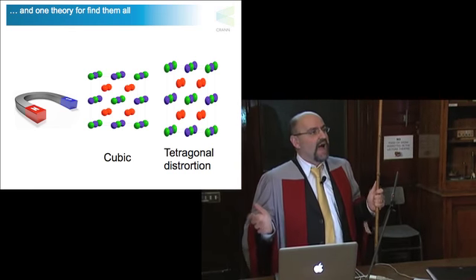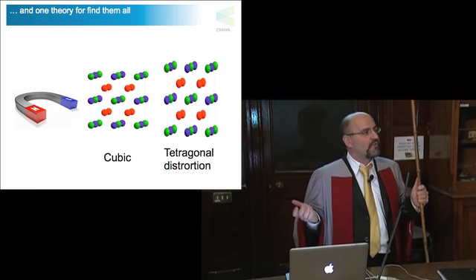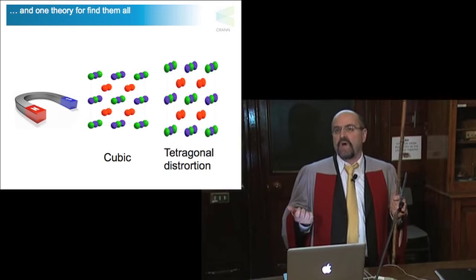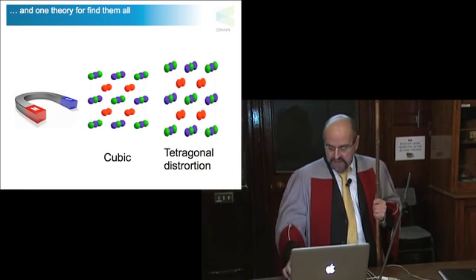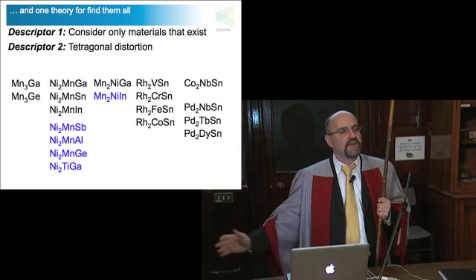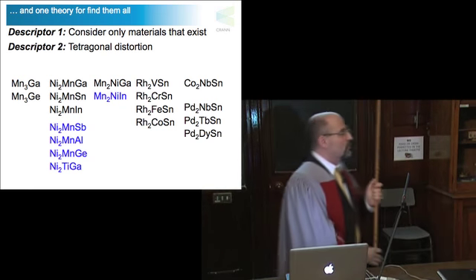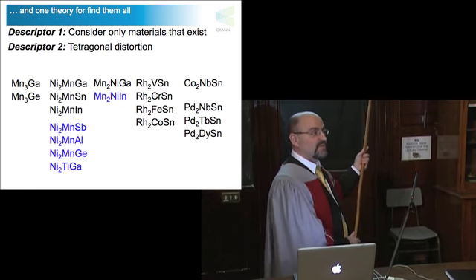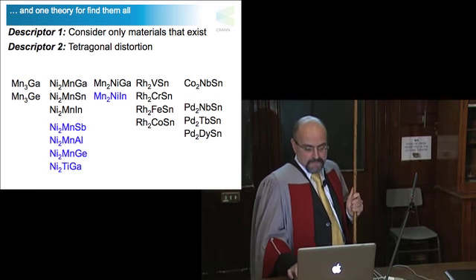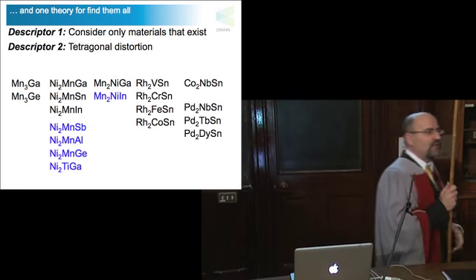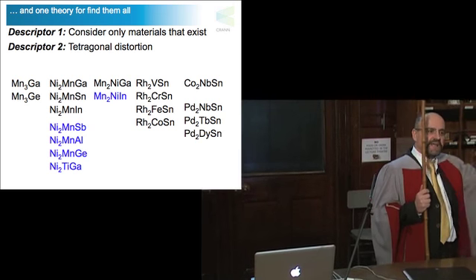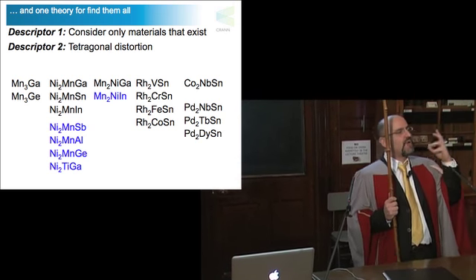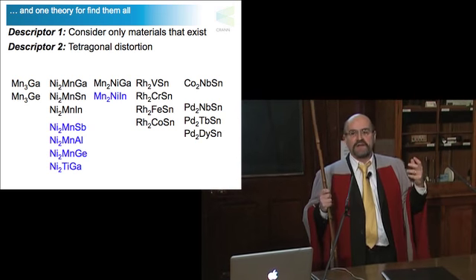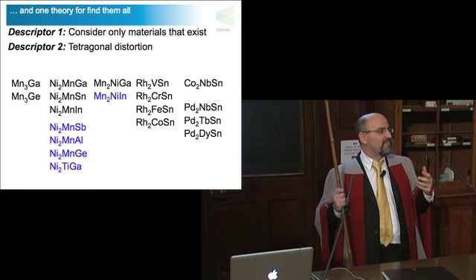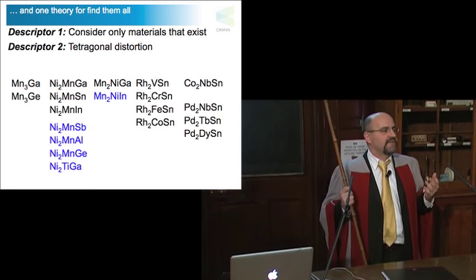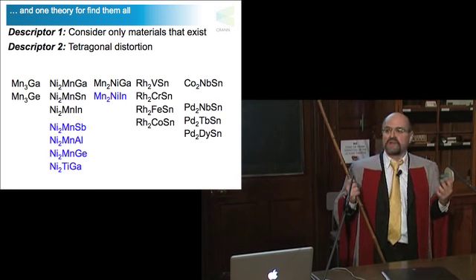So, as I said, here we don't want to produce new material, we want to understand why materials behave the way they do. So the first thing we did was, let's take all the existing ones and find out which of them actually, for some reason, make this distortion. And what we found out is there are only 13. And this is really somehow weird. You have 150 you can make, 300,000 you can potentially make, and only 13 really distort for one reason or another.